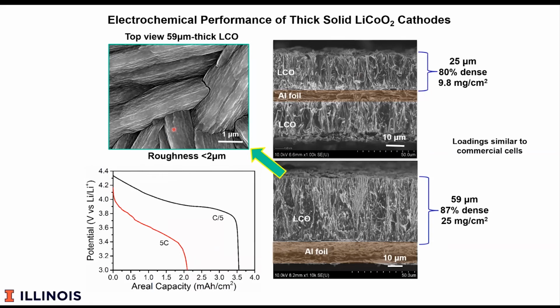Again, a little bit of a practical point, but the surface is quite smooth. That's important because if you're going to use a polymeric separator and you have a lot of needles coming off the substrate, they'll make a hole through and short it out. We were concerned about that, that the deposition would form dendrites, but indeed we see that is not the case.